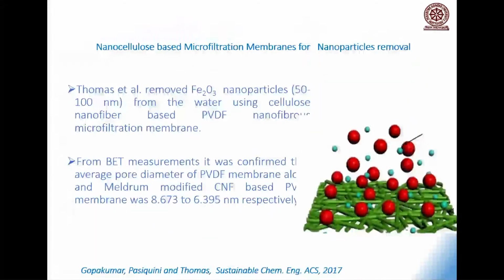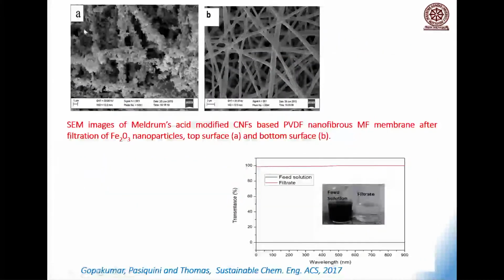Now, let me show you another interesting slide. Probably you know that water is increasingly contaminated with suspended particles, any suspended particle. So my PhD student Dibu and I, in cooperation with the Pasiquini in Brazil, decided to look at the suspended particles in water. We have not done any chemistry, we just gave a coating of the commercial filter with nanocellulose. Surprisingly, all the suspended particles were stopped at the top surface of the filter.